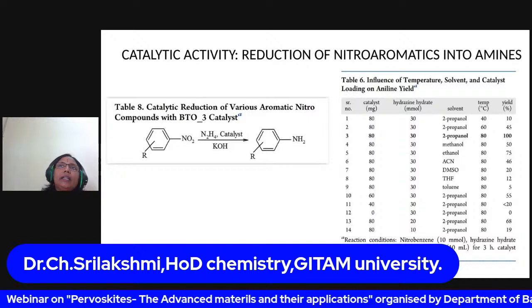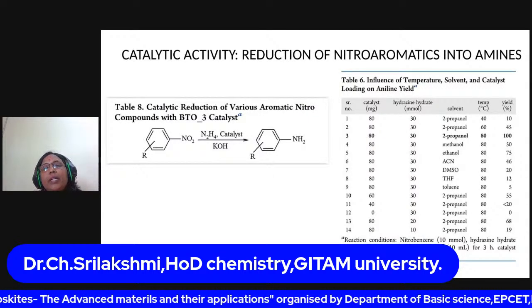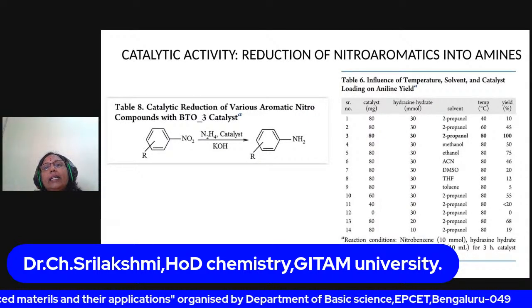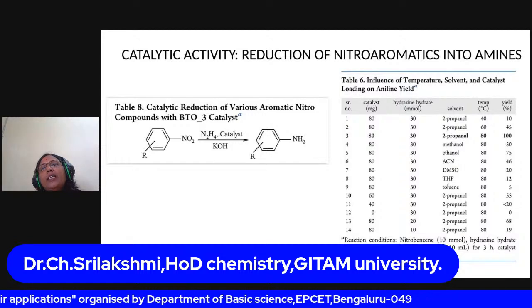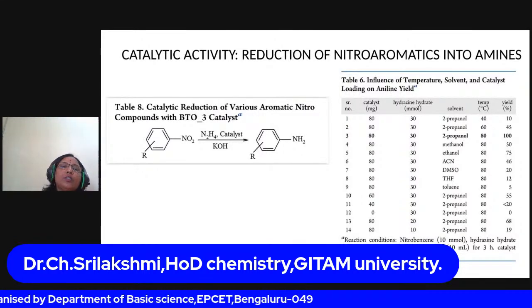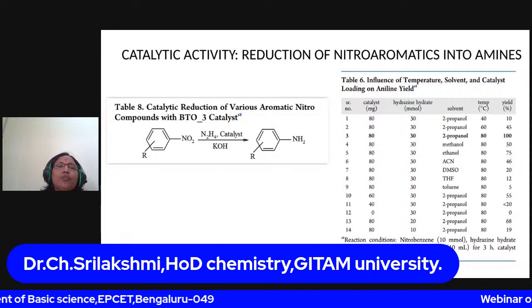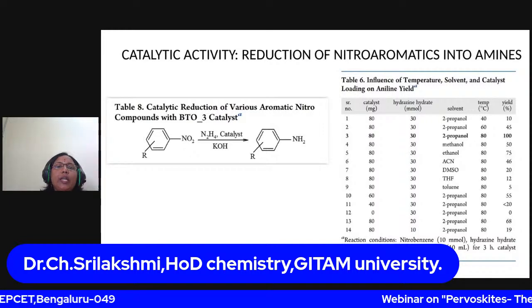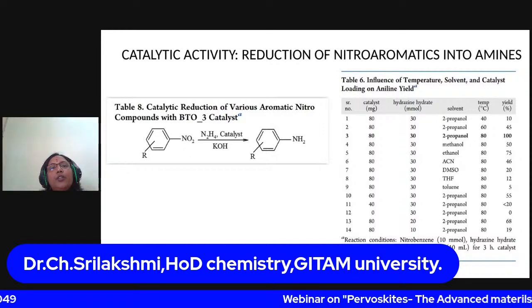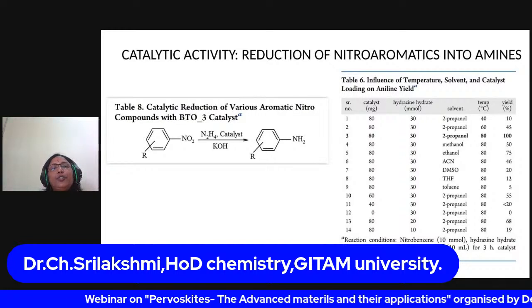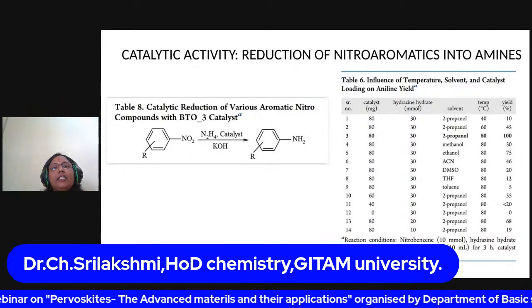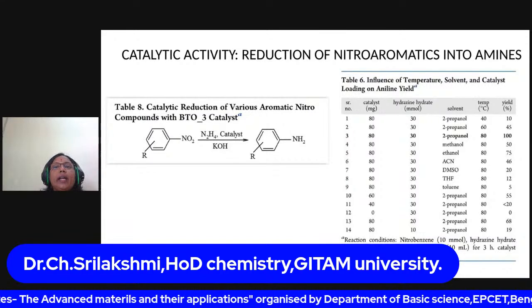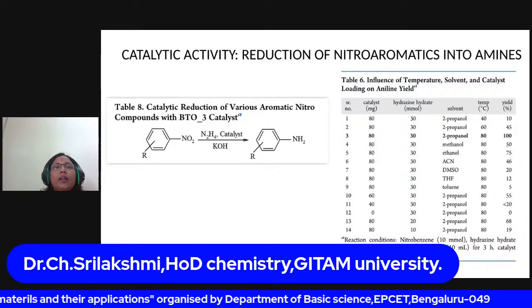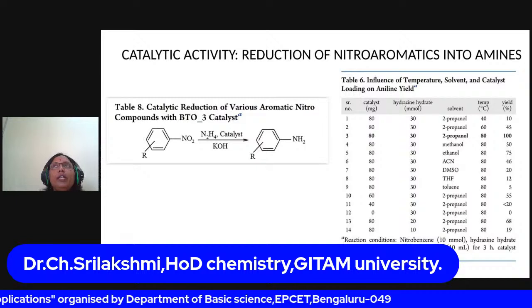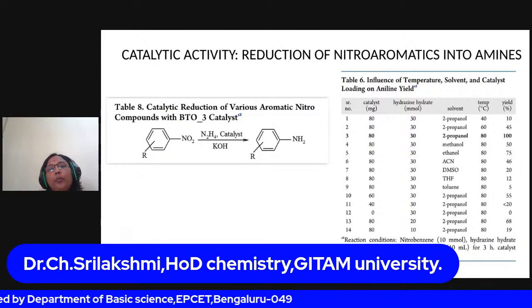So after we characterized our samples, we tested these materials for the catalytic reduction of nitroaromatics into amines. We transformed nitrobenzene into aniline using hydrazine hydrate as the reducing agent, with all the catalysts we have synthesized, KOH, and isopropanol as the solvent.